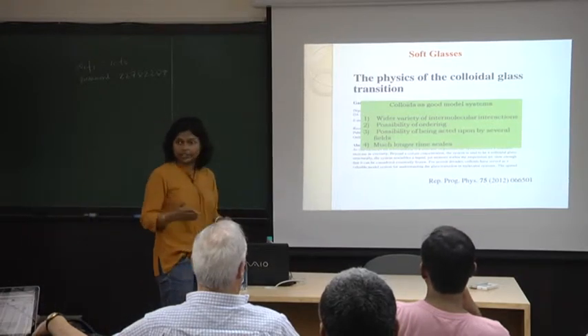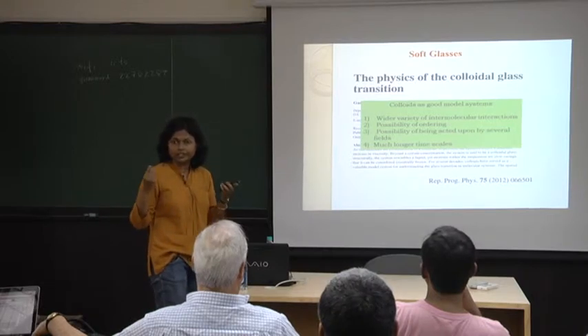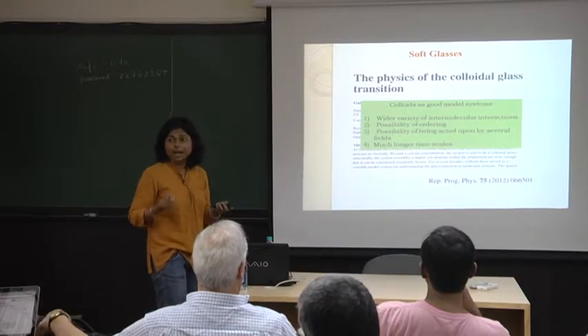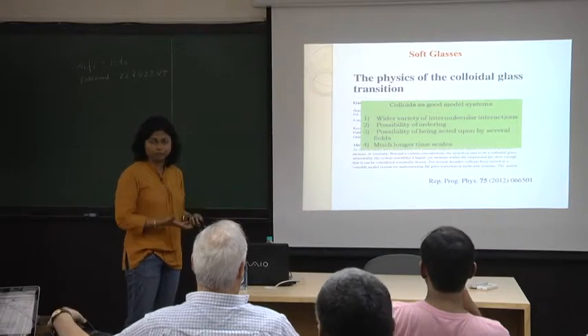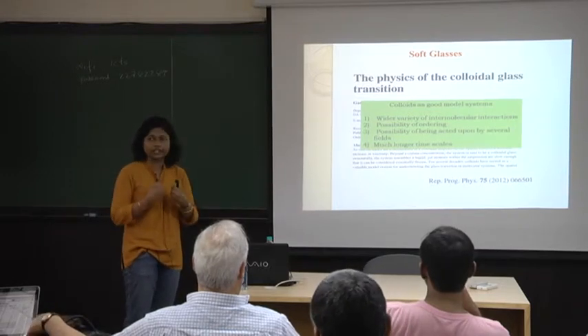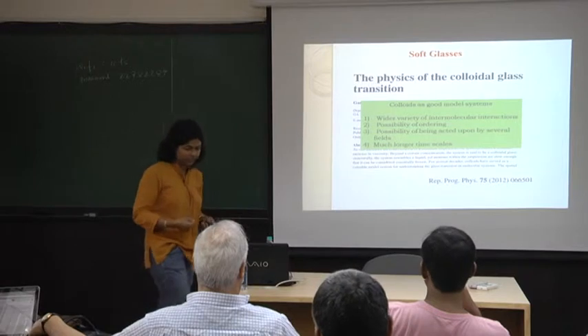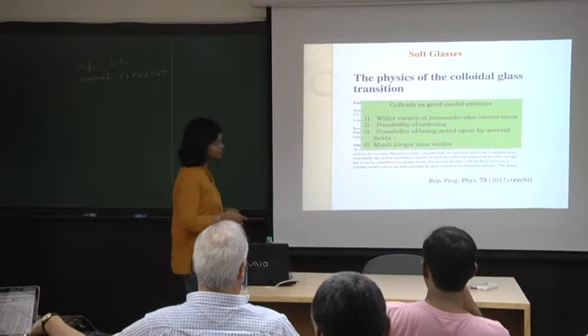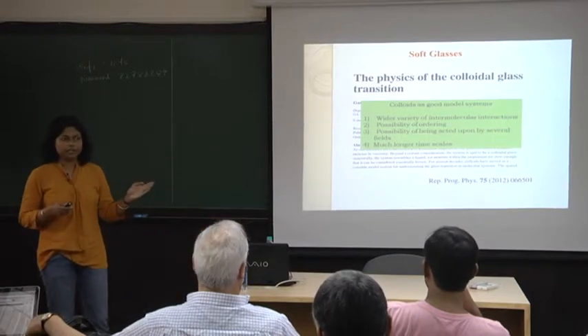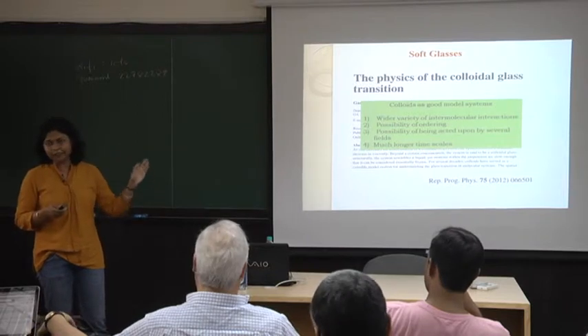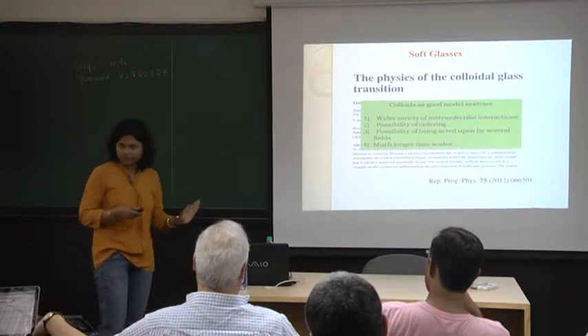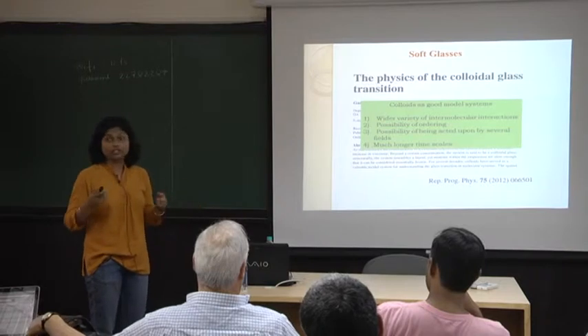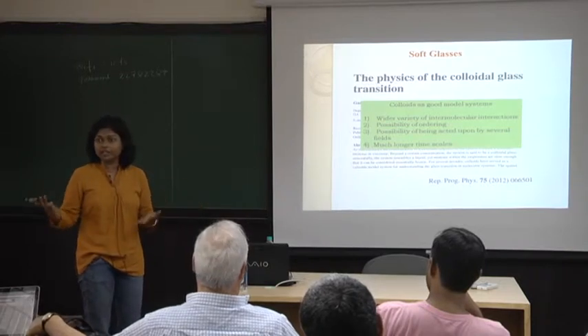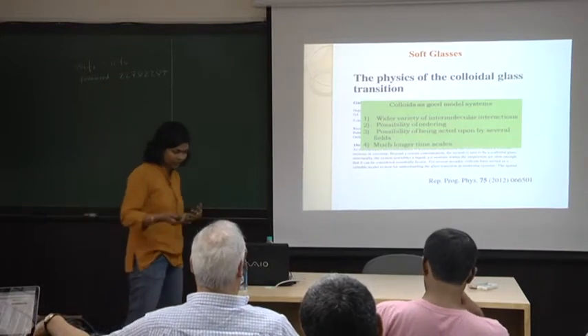You can also rejuvenate your colloidal glasses by applying very small forces that are actually accessible in the laboratory. This is possible for colloidal glasses because of the very soft interactions that the particles share between themselves. And these are much bigger particles. Bigger particles mean slower particles, and therefore you can actually look at them under a microscope in certain cases. You can also measure them in the laboratory by indirect techniques like dynamic light scattering, which is what we'll do.